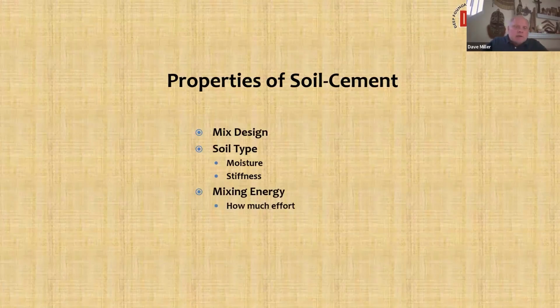Now, in the industry, they've established what's called a blade rotation number, and that's essentially the number of times a blade passes through the soil, so that you get an idea of how much mixing is in that. Some people call it an energy index. Some people call it just rotations, but it's all monitored to judge how much energy goes into that to evaluate the effectiveness of the mixing.